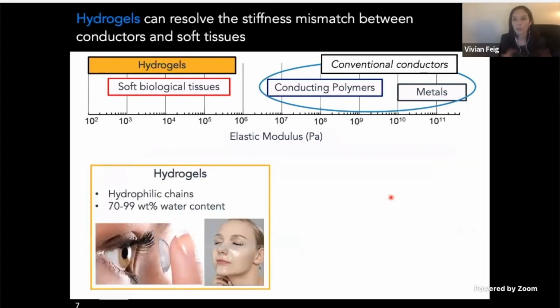So one way we can address this mismatch is to work with hydrogels, which comprise a very high content of water, up to 99% in some cases. And since we can think of water as a plasticizer for the polymer chains, hydrogels actually often have elastic modulus values that are within the same range as what's observed for soft biological tissues. And that's part of the reason why our bodies are already really used to intimately interfacing with hydrogel materials in our day-to-day lives, whether it's in the form of contact lenses that we put in our eye or various cosmetic